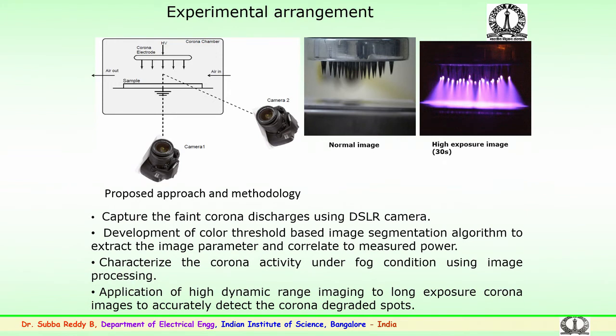Further, the measurement of corona performance in the field is normally done by looking at the corona discharges using UV cameras or corona cameras, where you could see the corona discharges impinging on the sample. A similar experiment or approach, particularly using normal DSLR cameras, was also tried out in the laboratory to see whether the power during the corona activity could be estimated by employing image processing techniques. So, a small attempt has been made to find out the possibility of this.